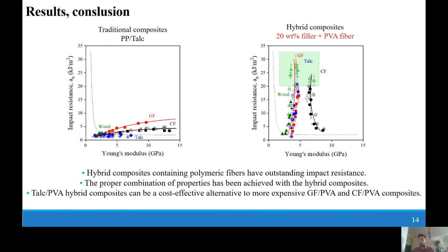The proper combination of stiffness and impact resistance has been achieved, and the results for talc PVA composites suggest that they could be a cost-effective alternative to the more expensive carbon fiber PVA and glass fiber PVA composites. We have found that sufficiently high impact resistance and stiffness can be achieved with different deformation mechanisms during failure.